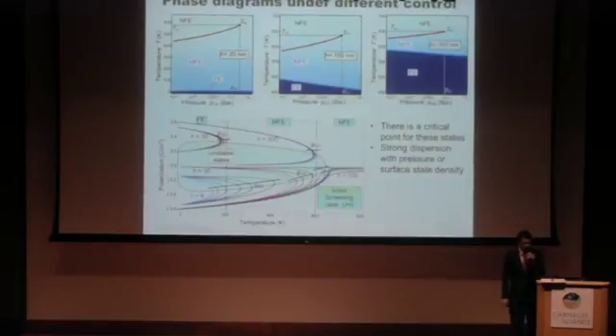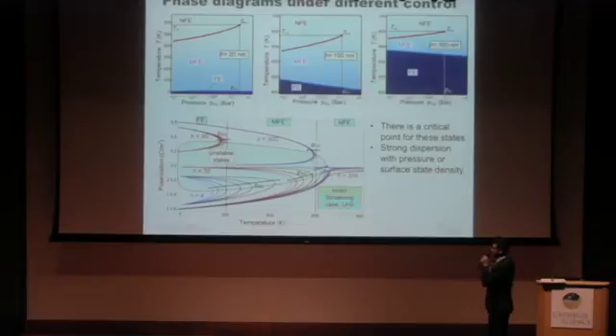You can go ahead and calculate what these phase diagrams should look like. This is an example where Anna has calculated the phase diagram for 20 nanometers, 100 nanometers, and 300 nanometers of barium titanate. You can see that this is as a function of temperature and pressure. This MFE is the so-called mixed ferroelectric state. You can see that this mixed ferroelectric state becomes less and less important as you go to thicker films, as you would expect. Interestingly, there are also these kind of strange critical points that exist in these phase diagrams.